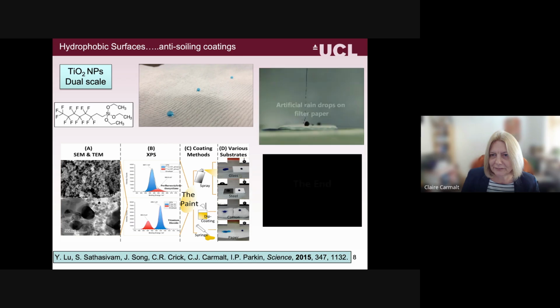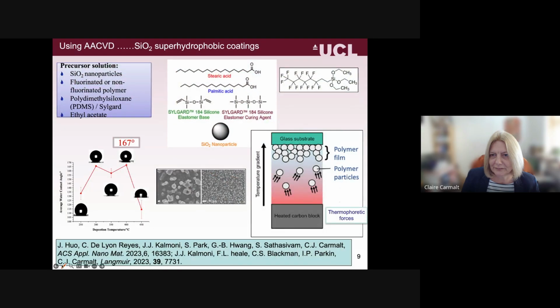So we had a look at seeing, just see if I can move on, could we use AACVD to try and grow thinner films and get them more transparent? And there's obviously sometimes a trade-off between the thickness of the coating and how rough they are and how hydrophobic. But we moved from using titanium dioxide to using silica because we thought that might enhance the transparency.